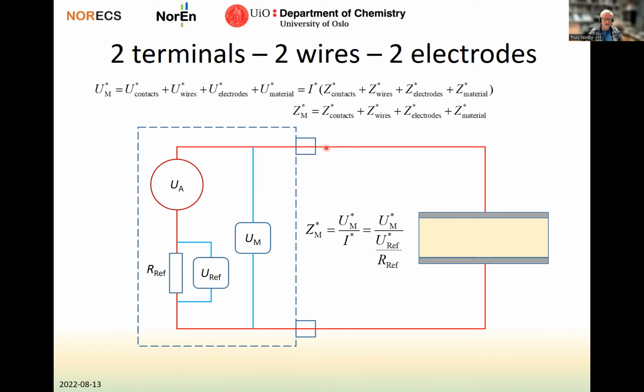So the total impedance you get from this ratio of the measured voltage and the current is the sum of the 4 impedances of the contacts, the wires, the electrodes, and the material. And seen from the instrument, this is the measured voltage divided by the current, and the current is the voltage measured over the reference resistor divided by the value of the reference resistor. It should be a small value, but it should be accurate and known to the instrument. So this is a normal 2-terminal, 2-wire, 2-electrode measurement.